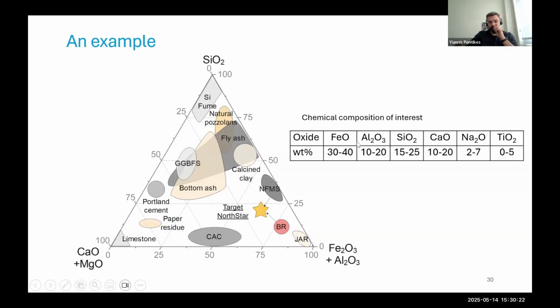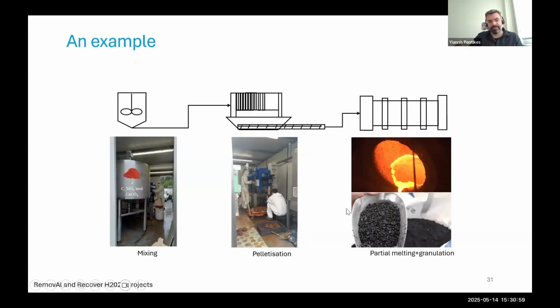So we're saying if you actually make it to that final chemistry, and we have papers supporting that, and Holcim has checked that, Heidelberg has checked that, Sika has checked that, the performance is good. Occasionally better than the blast furnace slag of today, but this is again for later to discuss. If we do that, then collectively, I think we create this new commodity that is now high in volume. And I also believe then the legislation will follow, because then you bring together so much more material that can actually be valorized in a high-end application, being blended cements.